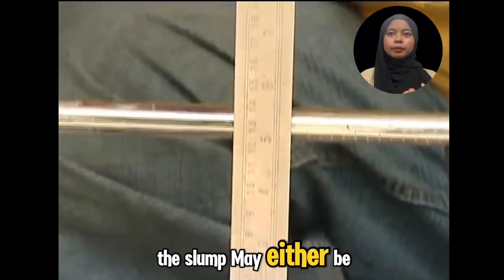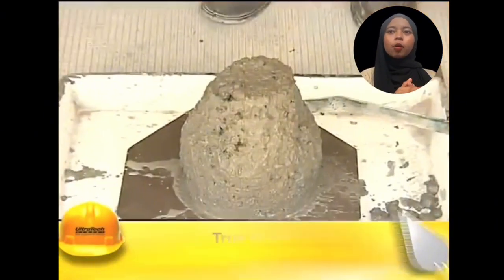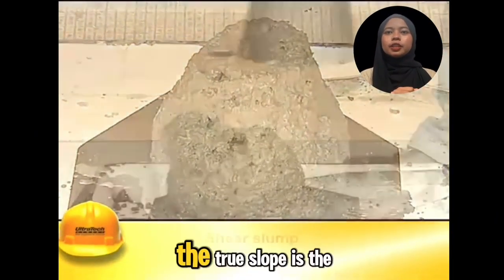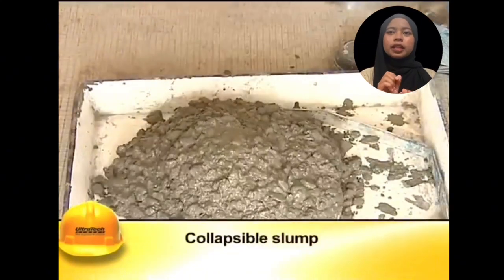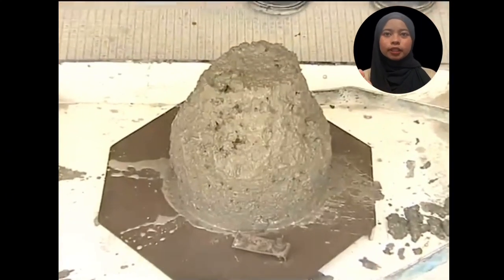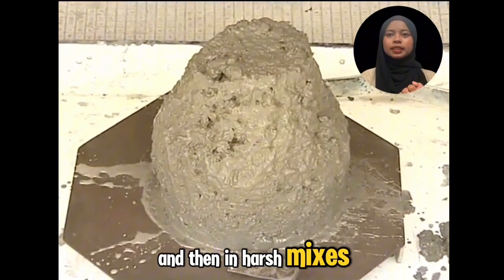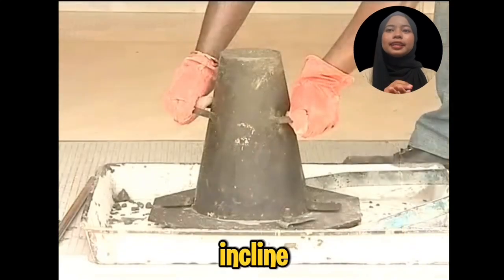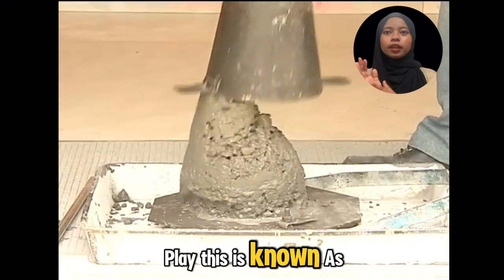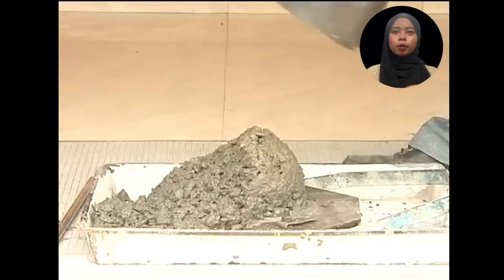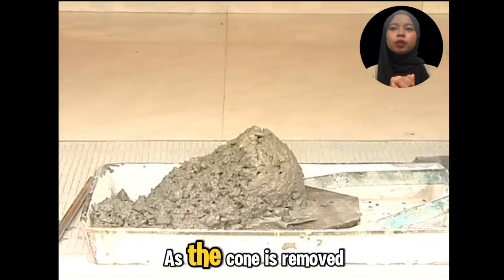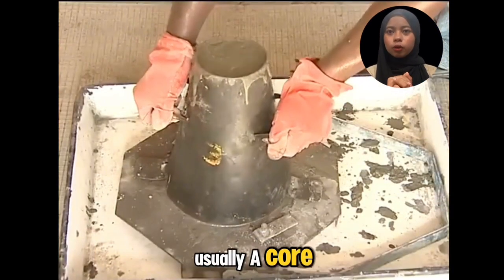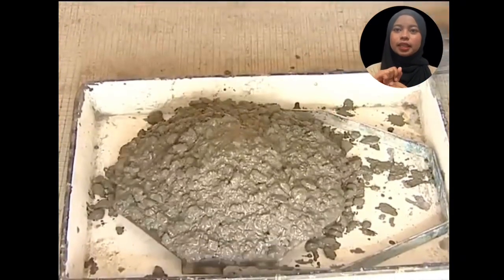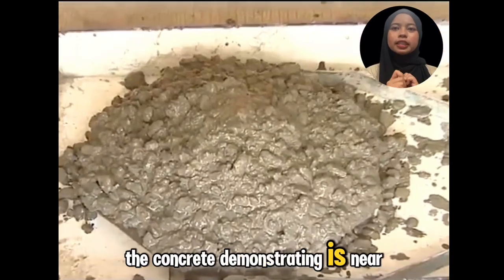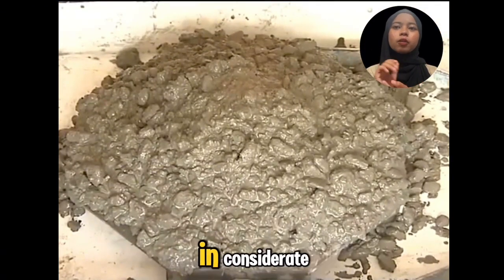The slump may either be a true slump or shear slump or collapse slump. The true slump is the desired form, a slump that we require. In harsh mixes, the concrete slides in an inclined plane. This is known as shear slump. In collapse slump, the concrete collapses as soon as the cone is removed, usually occurring in very wet mixes. Concrete demonstrating a near collapse slump is considered unsatisfactory.